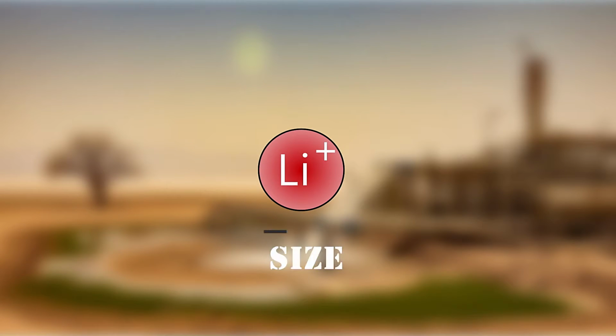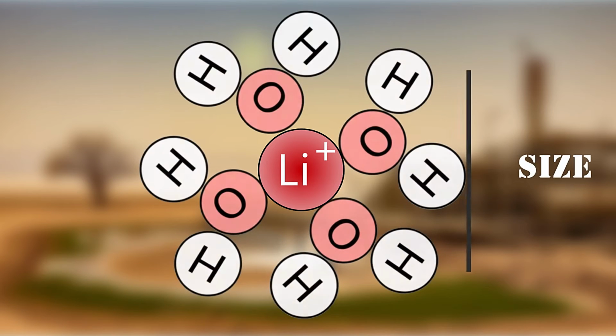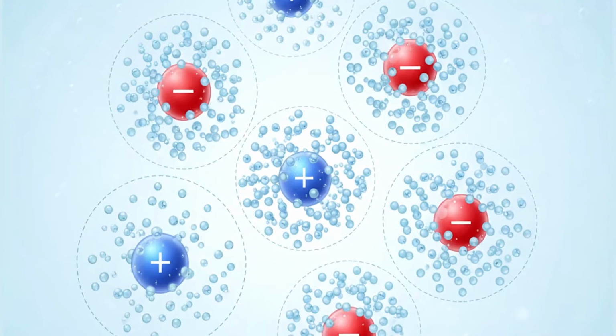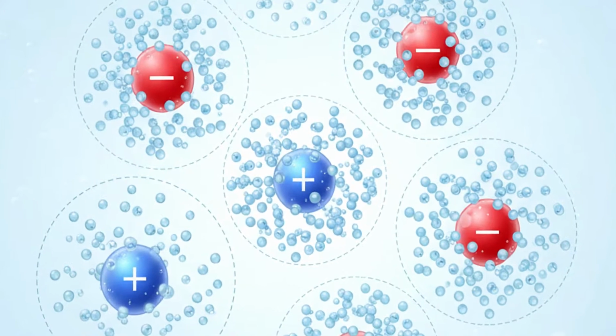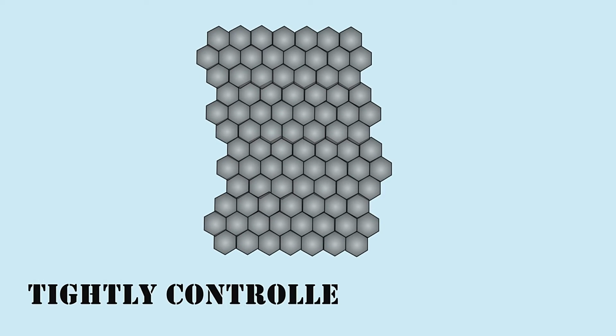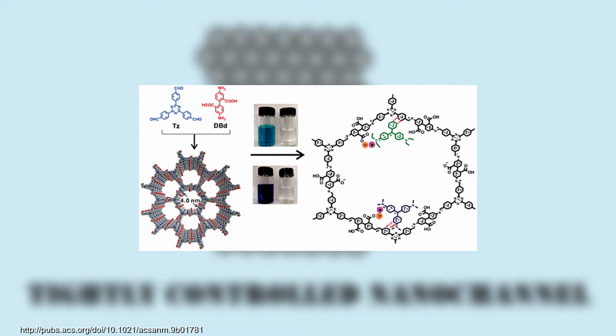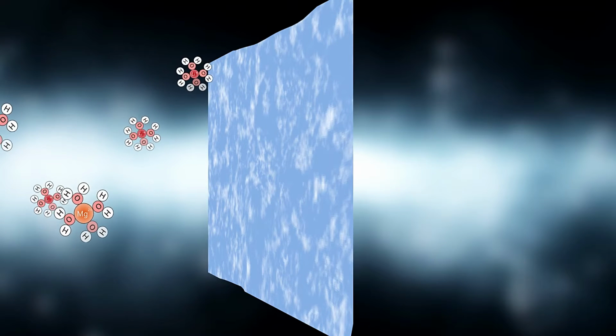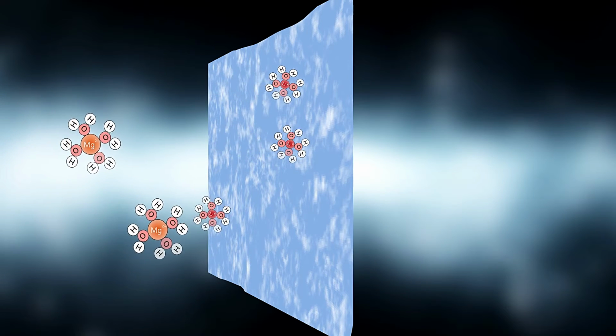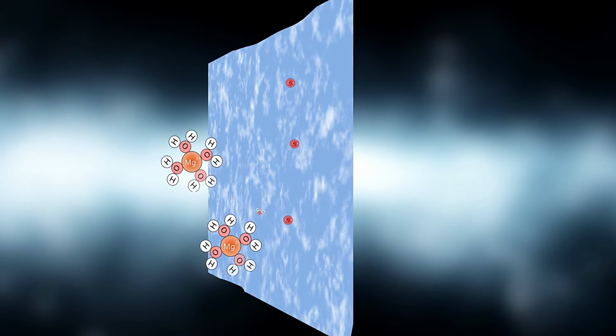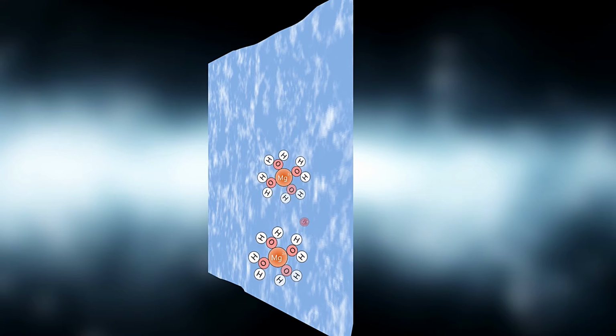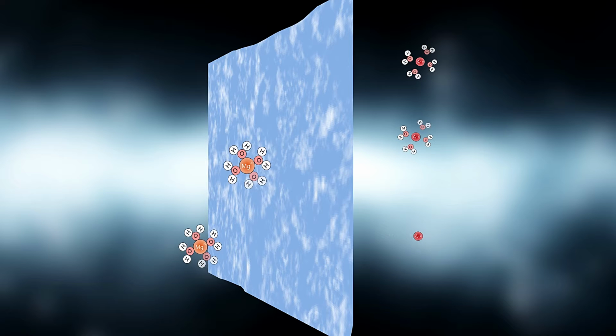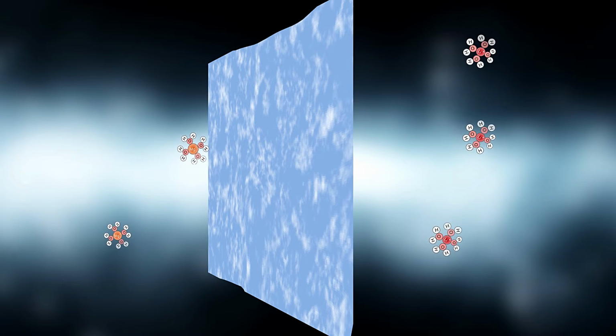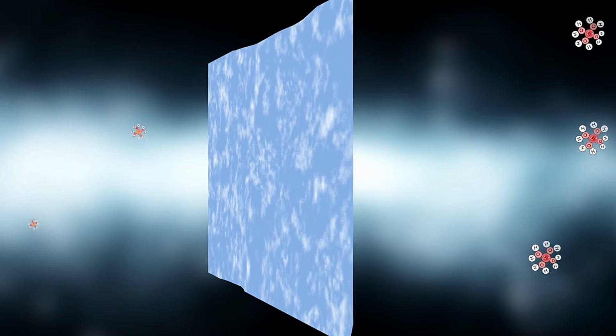The key isn't just the size of the ion, but the size of its water jacket. In liquid brine, every ion is surrounded by a hydration shell. To pass through a tightly controlled nanochannel, like those in advanced MOF membranes, e.g. UIO67, or covalent organic frameworks, COFs, the ion must shed some of that water jacket. Because magnesium holds on to its water molecules more strongly than lithium, it takes more energy for the magnesium to pass through the pore. The membrane selectively favors the ion that requires the lowest dehydration energy barrier.